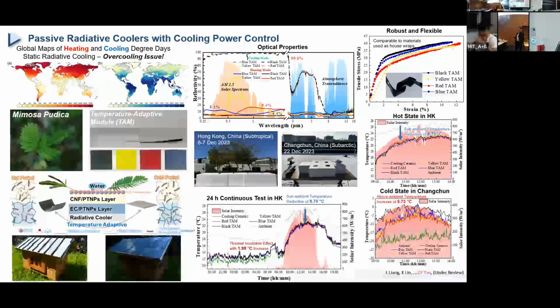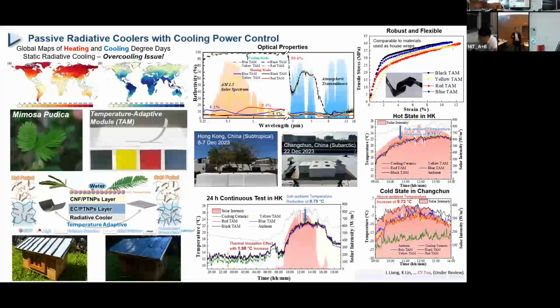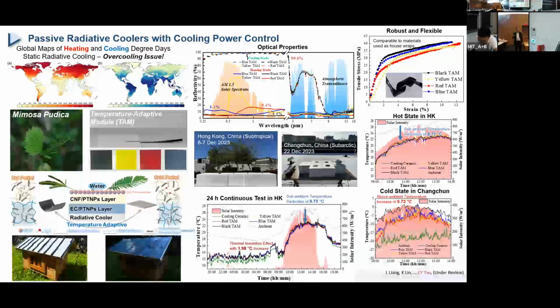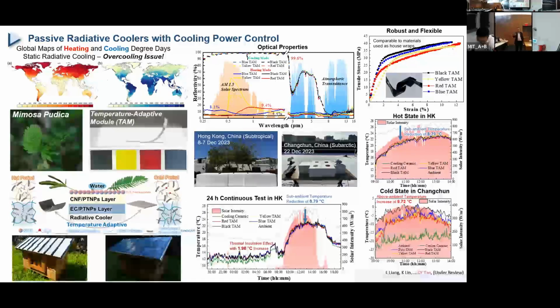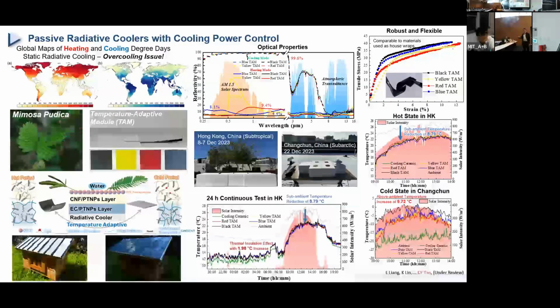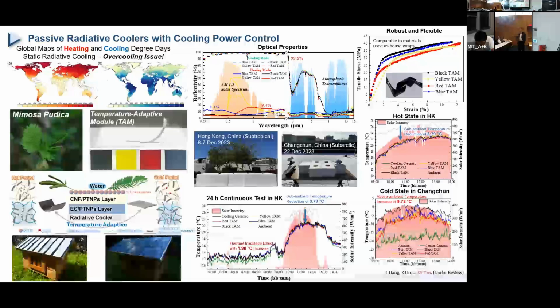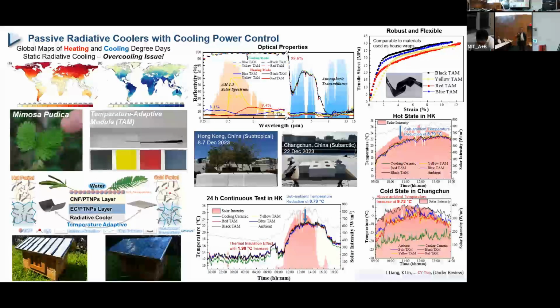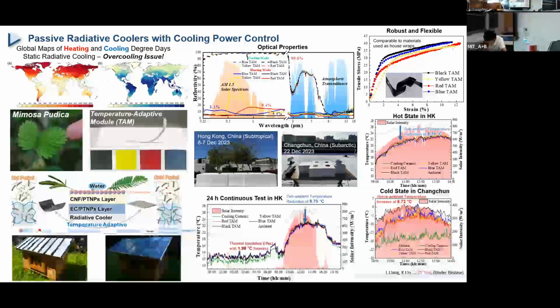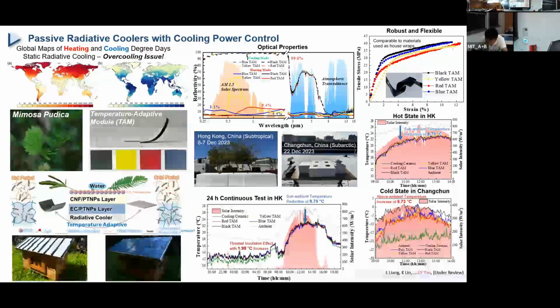We want to see whether we can have cooling power control for the passive radiative cooler. So we have developed a multiple layer cooler. There is a top layer that can go up and down according to the solar intensity, and the bottom layer is the normal passive radiative cooling layer. In summer, when the solar intensity is high, the top material rolls up, so the bottom radiative cooler directly faces the sky to perform radiative cooling. In winter, with a not very strong solar intensity, the top layer lays down and covers the bottom radiative cooler to perform solar absorption and keep the building warm.